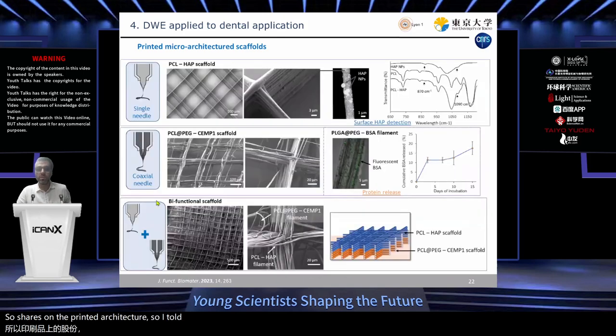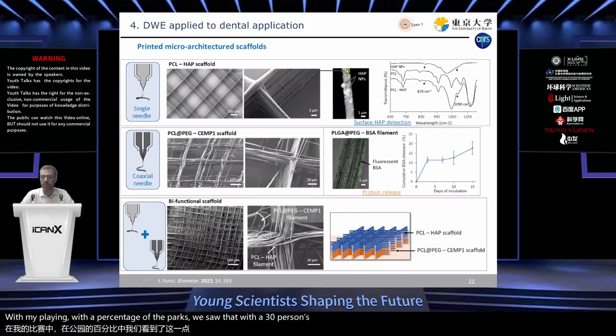So I told you that we wanted to use a bifunctional or hybrid material with two functionalities. So we put on one side hydroxyapatite nanoparticles. So the printing was very good. We saw here that we had the nanoparticles by playing with the percentage of the particles. We saw that with the 30% in weight of particles in the polymer, we were able to have a lot of particles at the surface of the filaments. So it's very important to have a good interaction with the cells. We also